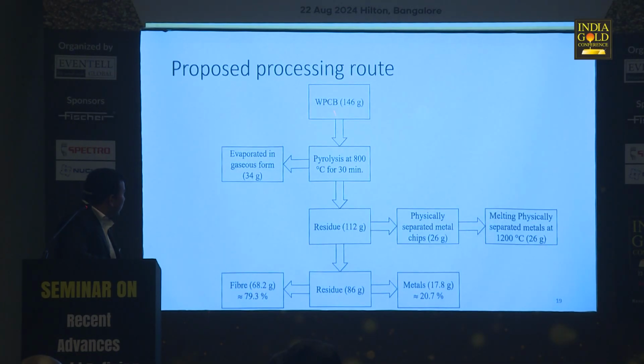Okay. So this is what we have come up with. We have waste printed circuit board. You can pyrolyze it at low temperature. There will be some gas evolution starting from 250 Celsius onwards. Then you have residue, which you can physically separate, and then you can melt, and then you have the copper-tin alloy containing your precious metals as well.